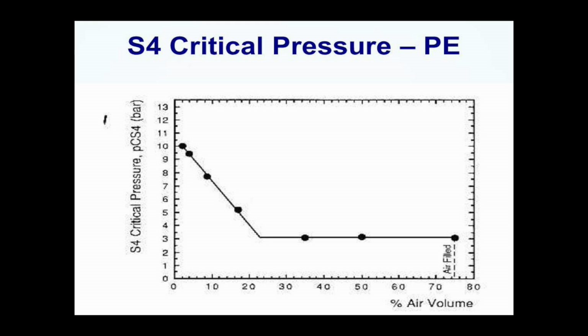And if you're looking at gas pipe, for example, then that would correlate. However, we also want to look at this for water pipe, when we have 100% water. We can also do the test in 100% water. As we can see, when there's zero air, or 100% water, we get a much higher critical pressure. Remember, the higher the critical pressure, the more resistant it is to these long-running cracks. As the air increases, the critical pressure decreases, and it starts leveling off.